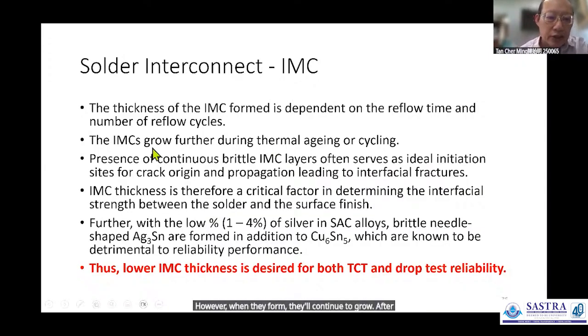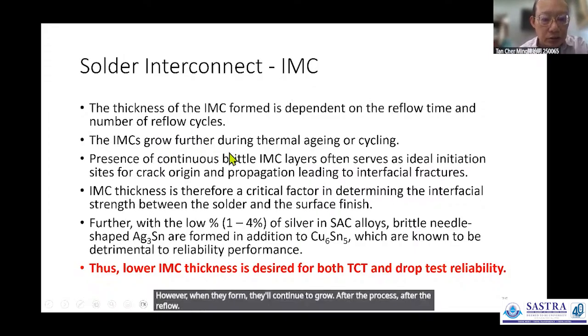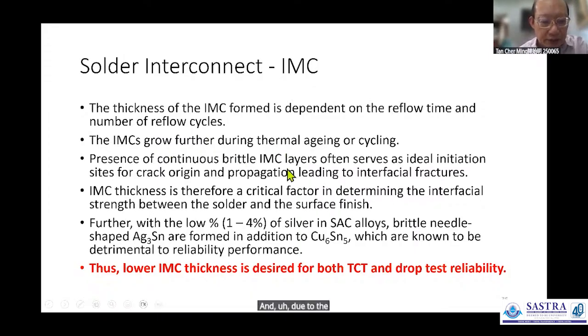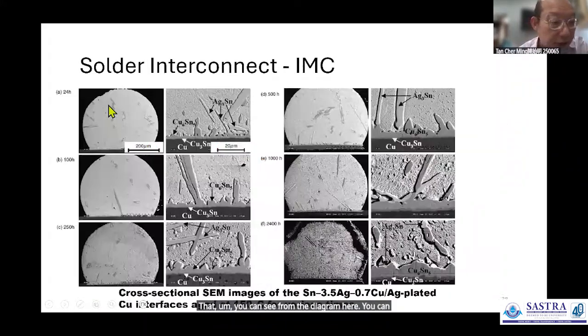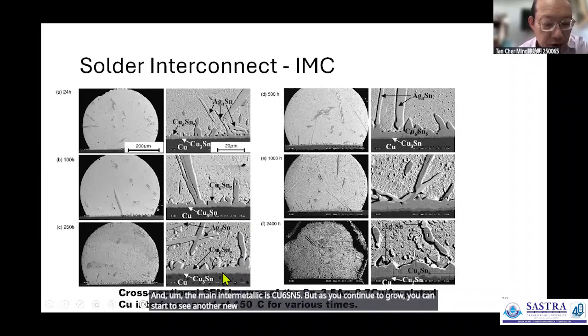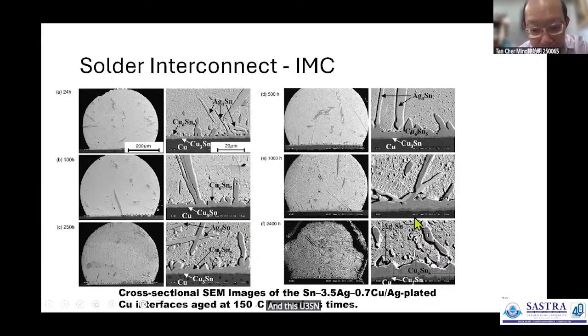After the process, after the reflow, they will continue to grow due to thermal aging and cycling. As you can see from the diagram here, at 24 hours you can see that there's intermetallic. As you continue on to 100 hours, this intermetallic will grow larger and larger. The main intermetallic is Cu6Sn5. But as you continue to grow, you can start to see another new intermetallic, Cu3Sn, and this Cu3Sn becomes thicker and thicker.